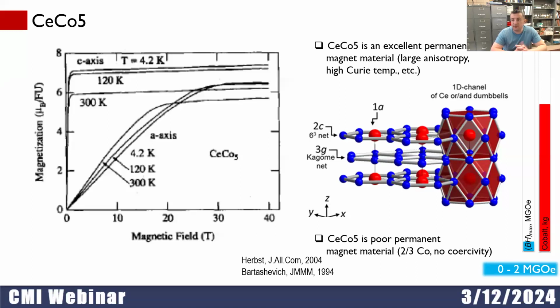Cerium cobalt 5 is isostructural with samarium cobalt 5. And everybody knows that samarium cobalt 5 has a maximum magnetocrystalline anisotropy. So it's very, very hard magnetically. And it's also because, in part, of the crystal structure. This crystal structure is unique.